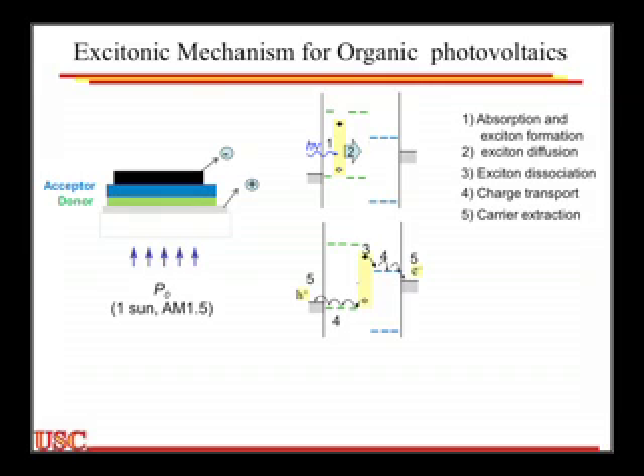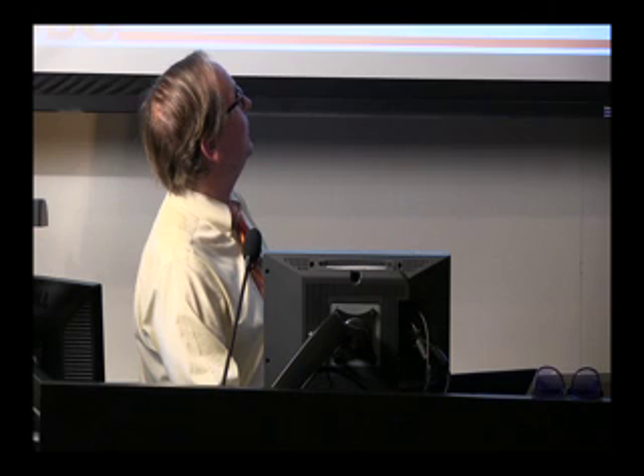And so if we start off here, we absorb a photon, we make an excited state or an exciton, the exciton diffuses to the interface between the donor material and the acceptor material. At this point, the driving force for creating the charge, creating the hole and the electron, is electron transfer from what I'm showing here as the excited donor to the acceptor. So once I've generated those two charges, they diffuse to the electrodes, and there's my photocurrent. And so you can think of it in these 5 steps, and it is pretty much in these 5 steps that the process occurs, but those actually lead to some serious limitations.